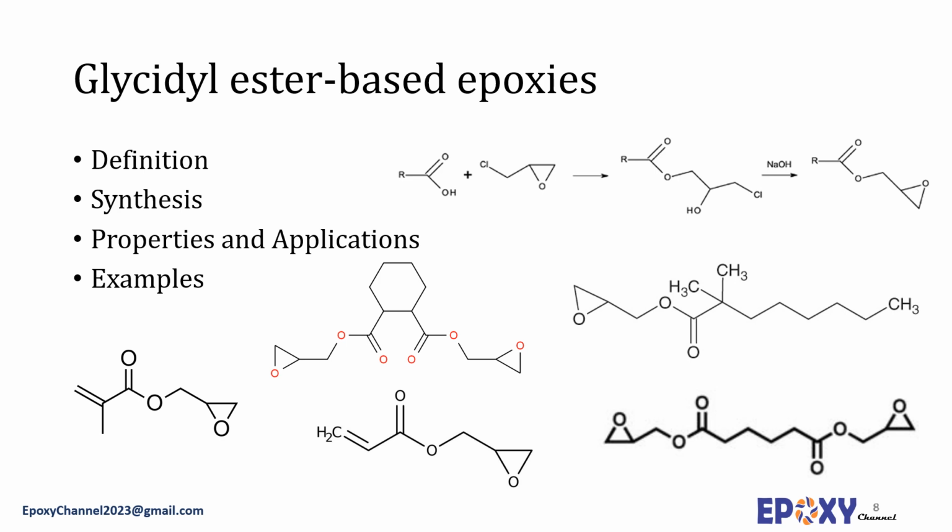These resins are typically more polar than glycidyl ethers and display low viscosity at room temperature, for example 500 millipascal/second. But they have similar reactivity to bisphenol A epoxy resins. These features mean that they can be used as reactive diluents used to modify and reduce the viscosity of other epoxy resins.